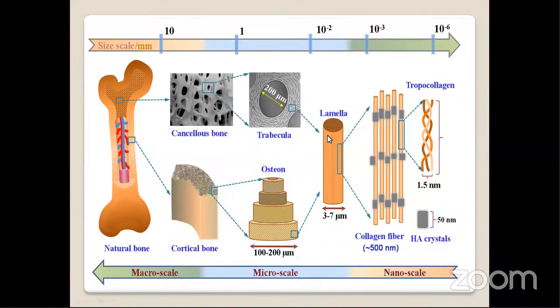Okay, so here this lamella will have a diameter of about 3 to 7 micrometers. One lamella consists of so many fibers like this. This is called collagen fiber, approximately in the range of 500 nanometer. Okay, this collagen fiber is connected through hydroxyapatite crystals. See this black color one. This black color is hydroxyapatite crystals. This is in the size of 50 nanometer. But the strands are made up of a tropocollagen structure having a thickness of about 1.5 nanometer.